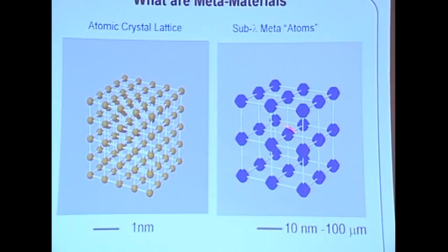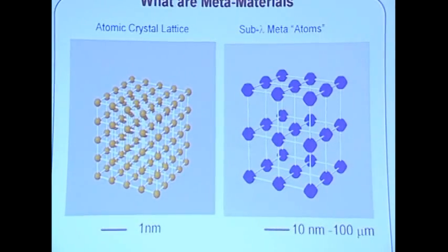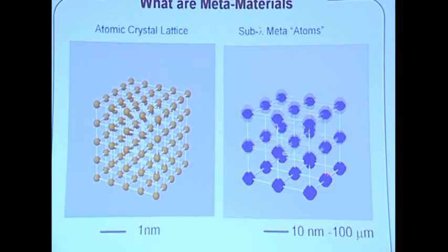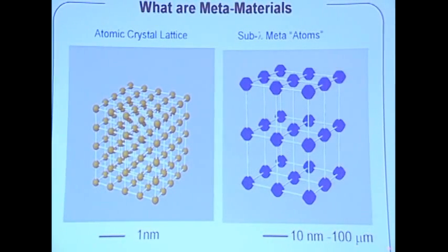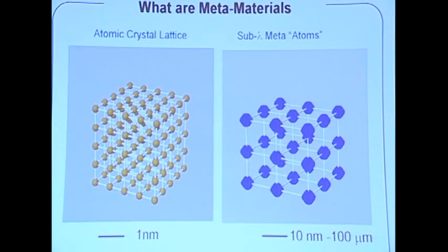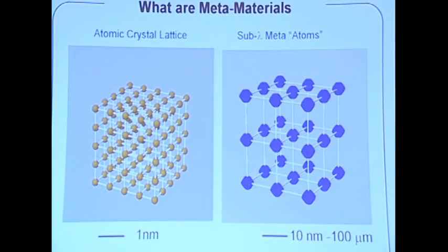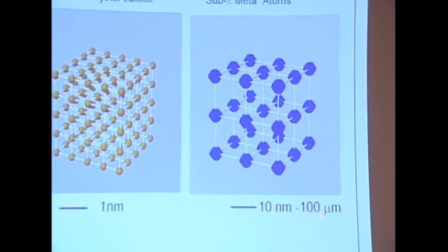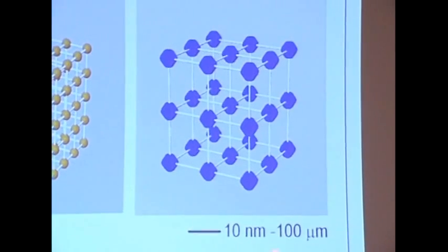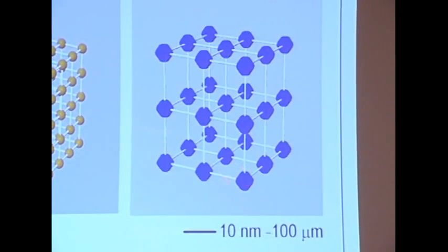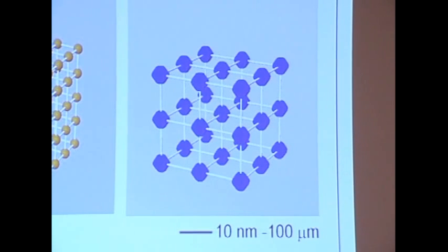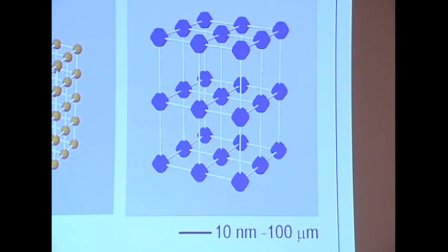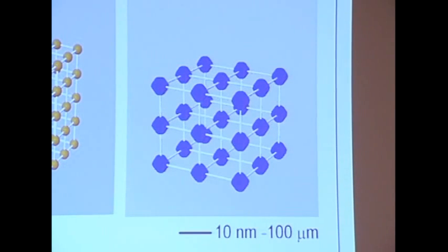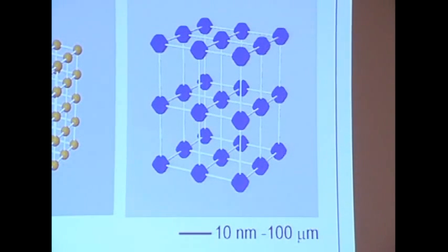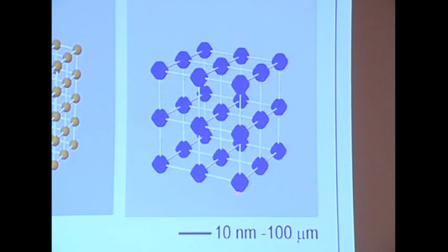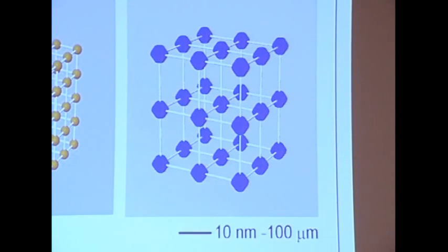So this is scalable. Now, what we learn is you can build something similar to atomic scale crystals. But now, because it is relatively larger, it can be 10 nanometers all the way to, well, right at 100 microns, but could be much larger. Now we are also working at the centimeter scale. So the lattice size depends on how you fabricate it, and it can be quite a different scale. Also, each of these, quote unquote, meta-atoms can be a physical entity to which you ascribe properties, such as putting a little current on it to have an artificial spin. And you can have a very soft static charge, and you can have ionic crystals.